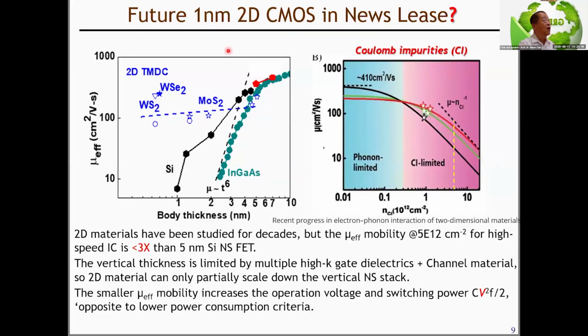You may have heard from the news about the future two-dimensional material for manufacture. The 2D material, however, has been studied for a decades-long time. But the effective mobility at 5E12 cm⁻² for high-speed IC is still 3 times lower than 5 nanometer silicon nanosheet FET used for production this year. Besides, the vertical thickness for a nanosheet transistor is limited by the multiple high-K gate stacks plus the channel materials. So the 2D material can only partially scale down the vertical nanostack.